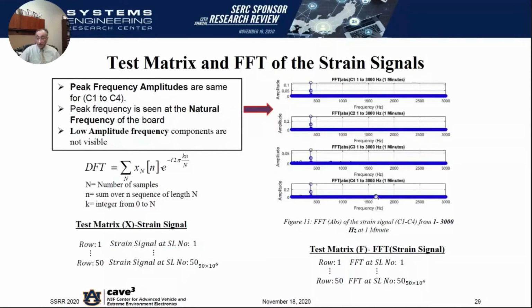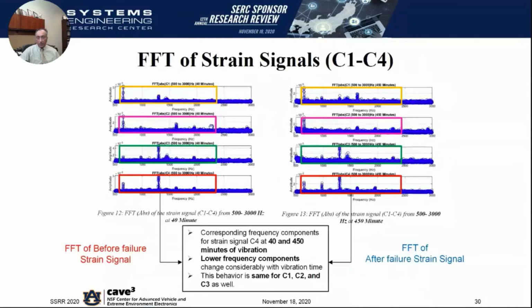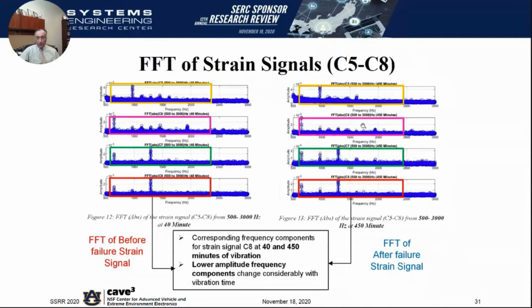So if I was to compare different sensor locations, first thing I see is if I were to just take an FFT, I actually don't see very much difference visually. So what we have done is we have tried to segment the data into a narrower band, looking at a band of 500 to 3000 hertz. And if I step forward in time, so this is 1 minute data. If I step forward in time to 40 minutes, now I can actually start to see features. And there's a variance between the different sensors. There's also changes between before failure and close to failure. Failure happens close to 450 minutes for this particular board assembly, as I will show you in a few moments. So you can actually see that the feature vector changes before and close to failure. Similar changes, C5 through C8.